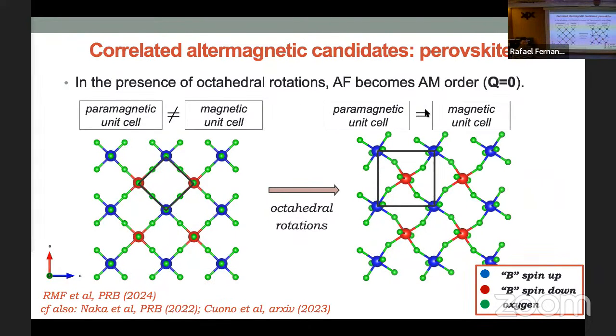So let's just go over and show you that this is indeed an altermagnet, right? So this is the ideal perovskite structure. The paramagnetic cell in itself is different than the magnetic one. So I'm showing this again, a projection to make life easier. The moment I have octahedral rotations, as you can see now, my unit cell has, at least in this plane projection, double the size, and it matches precisely the magnetic unit cell. So this is a good candidate for altermagnet. So let's see what operations I need to do to compensate for time reversal.